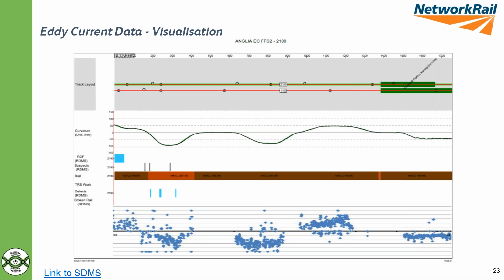And it maps as you would expect. You can see cracking on the high rail of the curves. So where the curves reverse, the RCF changes. What you also see is cracking on the low rail, perhaps because of lower speed freight traffic on these particular routes. So it's not only the higher speed passenger traffic affecting the high rail, but we also get corresponding damage.